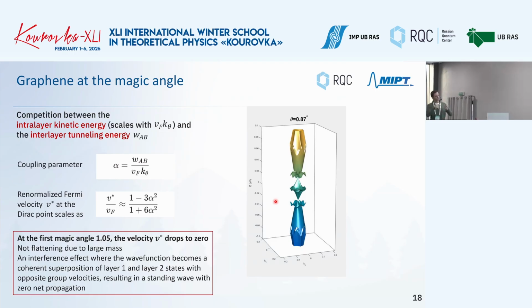And then if you move further, there are the second magic angle and so on. So it's more complicated there. But the main thing is that by changing the angle between the layers, you can obtain not a linear dispersion but flat bands, and they happen due to the interference between all these things, which I explained here on the left.